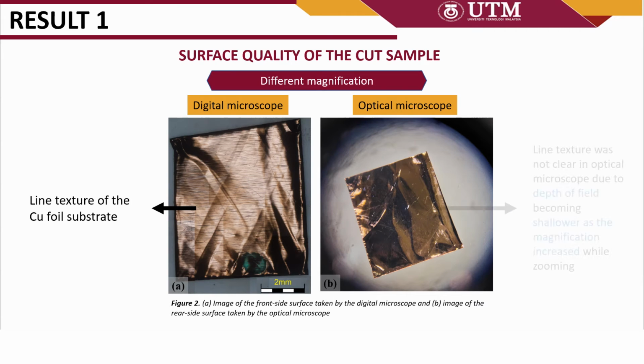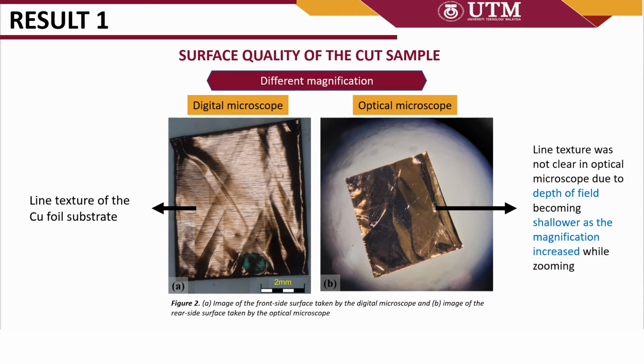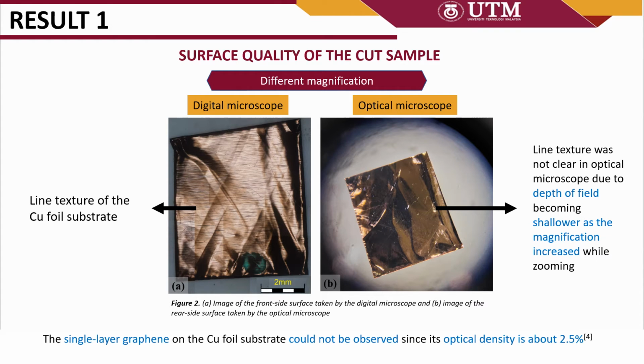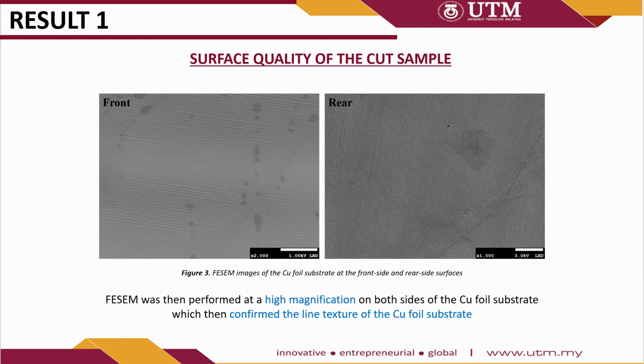Other than that, line texture was not clear in the optical microscope due to depth of field becoming shallower as the magnification increased while zooming. Additionally, the single-layer graphene on copper foil substrate could not be observed since its optical density is about 2.5%. FESEM was then performed at high magnification on both sides of the copper foil substrate, which then confirmed the line texture of the copper foil substrate.